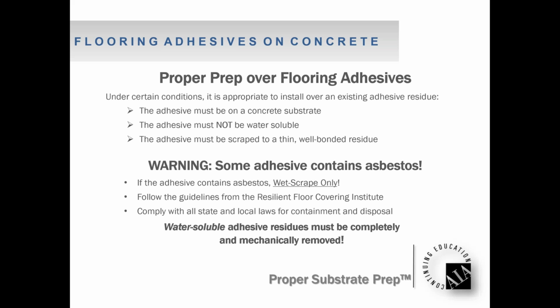It's a performance issue. If you have thick adhesive, foot traffic over top of that installation could allow that adhesive to move, and then the adhesive fails. And we've seen it time and time again. You have a disbonded patch leveling product, you look at the underside, and there's adhesive stuck to the underside. You look at the concrete, and you still have adhesive on the concrete. The adhesive failed. So it's critical to scrape it down to a thin, well-bonded residue.